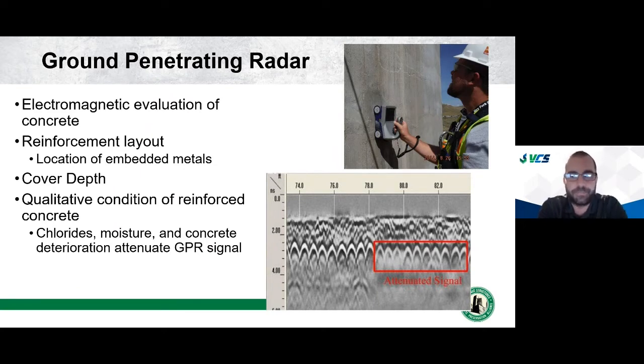So what we can do is scan a structure, map out the reflections, and areas of attenuation are an indication of a potential issue. Now, one thing to be very cautious of, and I think commonly in the industry this gets misinterpreted, is, I often hear this when I talk about GPR. They'll say, "Oh, I hired someone with GPR to go out and do a delamination survey, and it didn't work. There was no correlation." And I'd be like, "Yeah, exactly." Because GPR is not able to do a delamination survey.